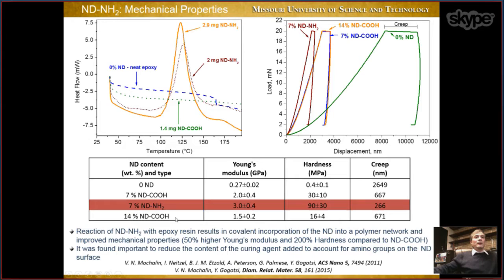And aminated nanodiamond works even better when you double the concentration of non-aminated material. So if you use 14% of carboxylated nanodiamond, you are still way below the hardness achieved with aminated material. And we also reduce creep. So these are indications of what we can achieve by designing nanodiamond for this particular application, and by then covalently incorporating this nanodiamond into the structure of composite.